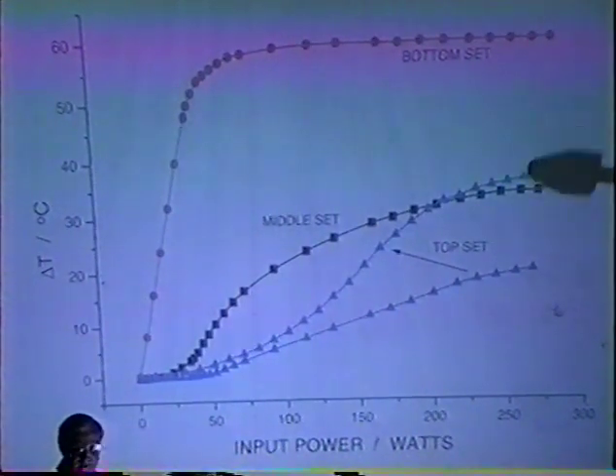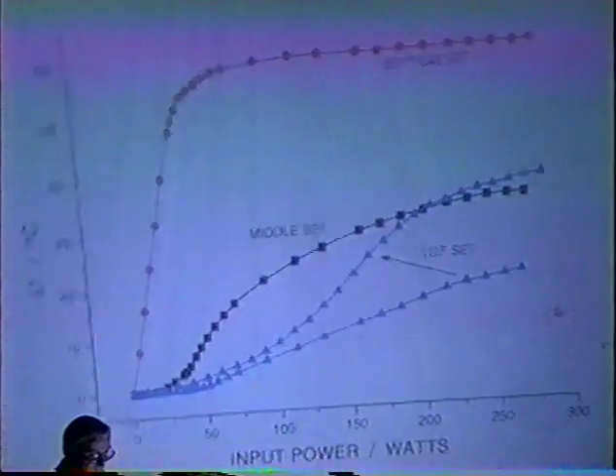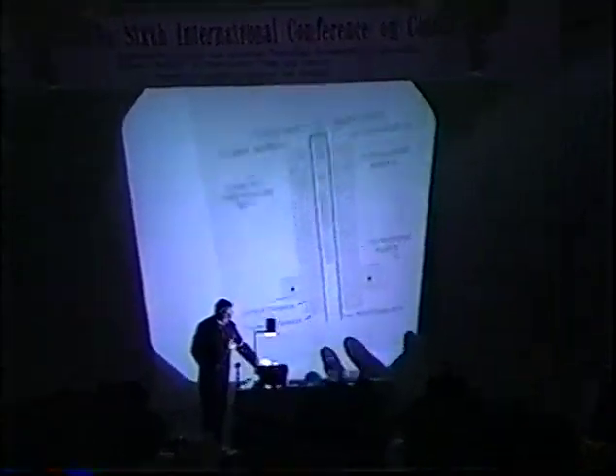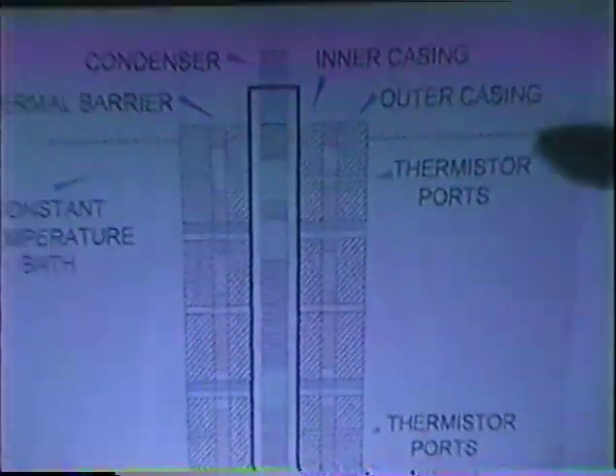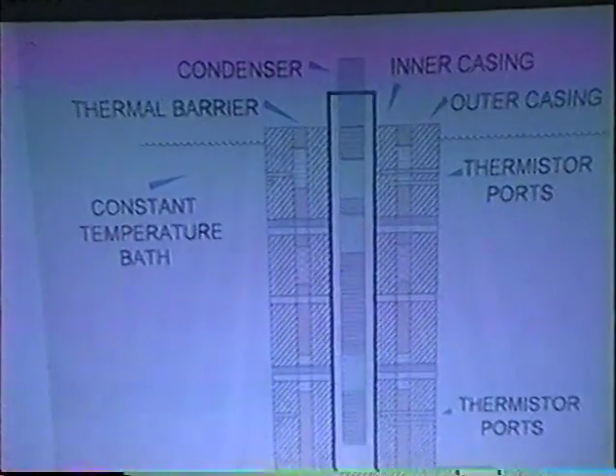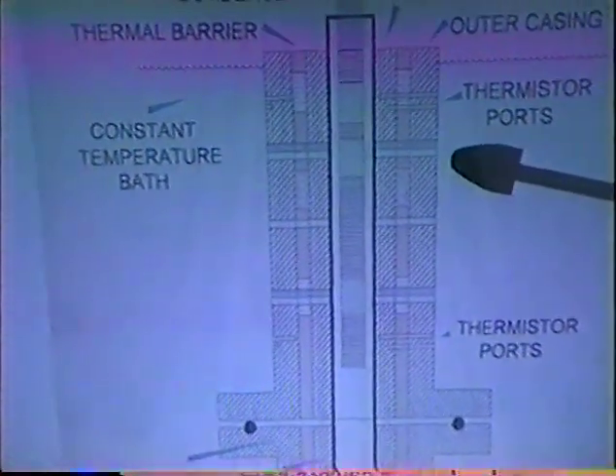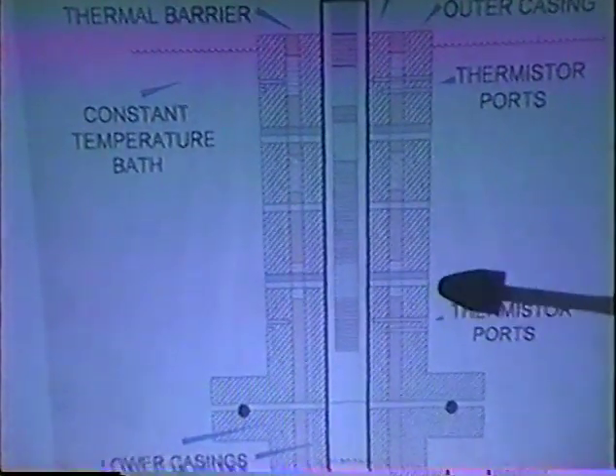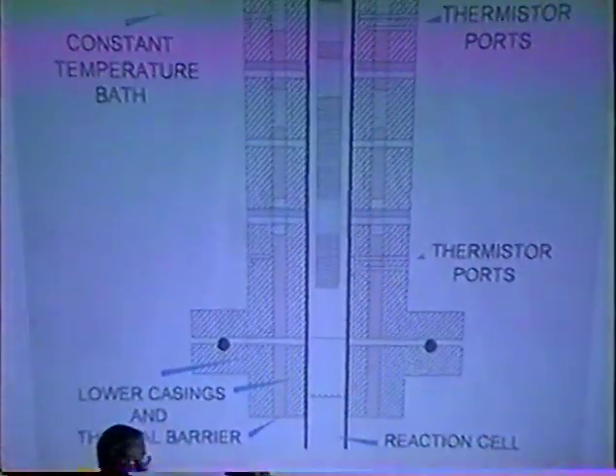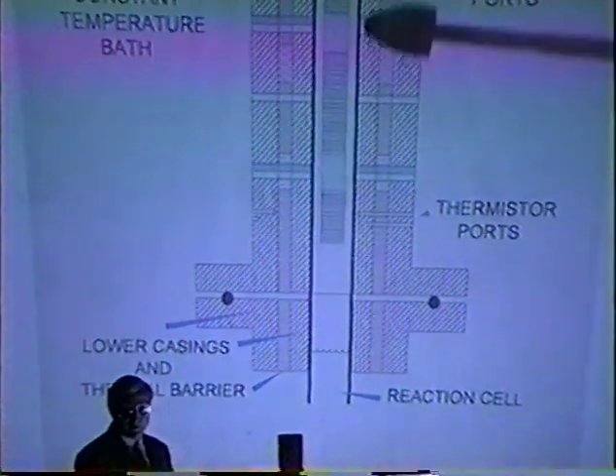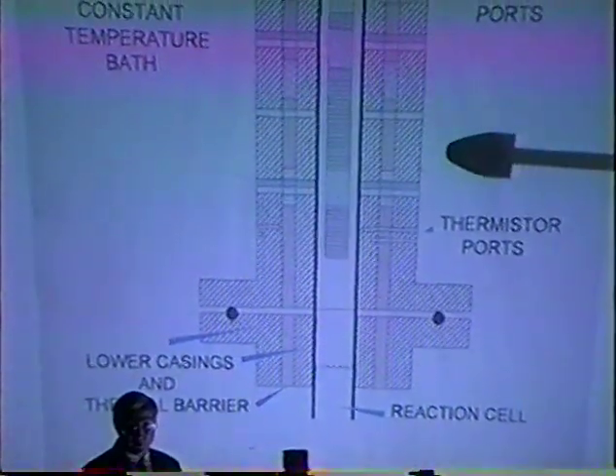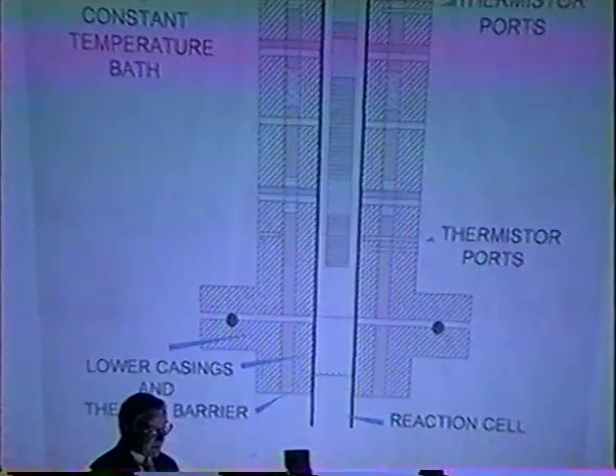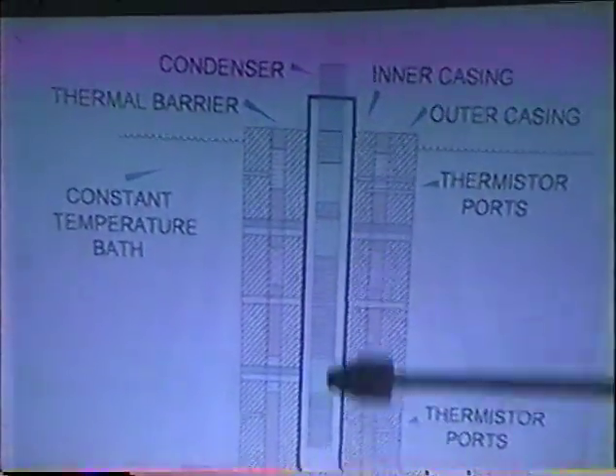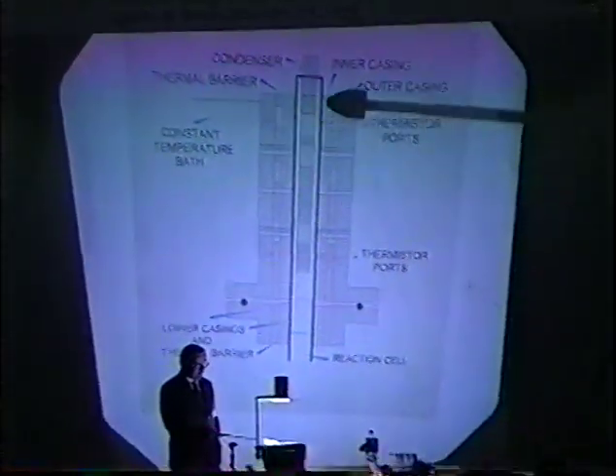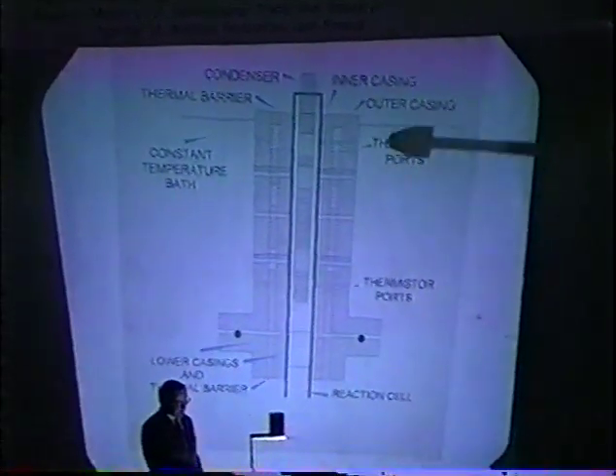You can even change the absolute magnitudes of the sensitivities by changing various segments of the calorimeter. Specifically, you can change the structure and the materials used in the center condenser. You can insert insulators across the entire barriers, making further separations. This helps in linearity. You can cool these bottom sections with respect to the top sections by putting thermal shorting bars, in other words, metal rings. You can open up the center of the insulating material, the condensing plug here, in order to get hotter vapor to the top thermistors.